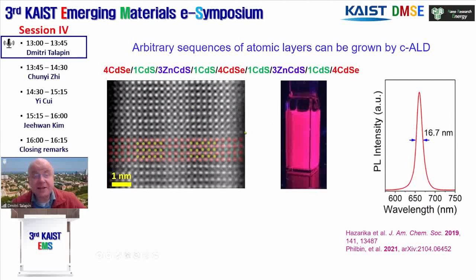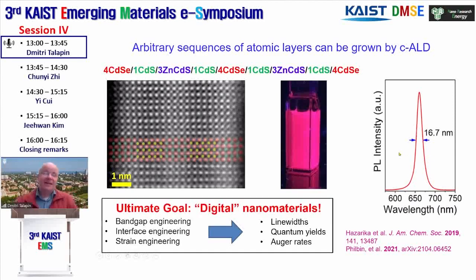So, for example, after that many layers of colloidal ALD, the ensemble emission spectrum will have a pretty good Lorentzian line shape and extremely narrow line widths. And ultimately, it brings us one step closer to our goal that we can define as digital nanomaterials, where we can connect physical concepts such as band gap engineering, interfacial engineering, strain engineering, and map them on experimental observables that we need for optimization of device operations. And we can close the loop between theory and experiment, where we really know what we grow.